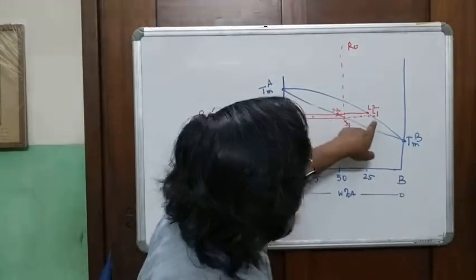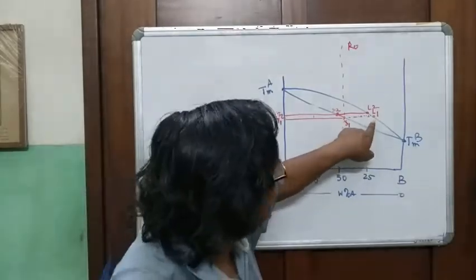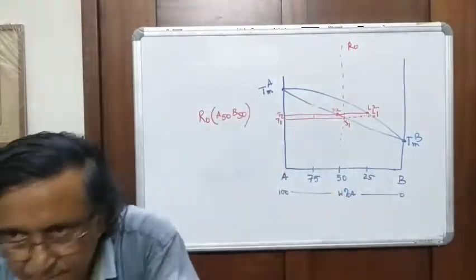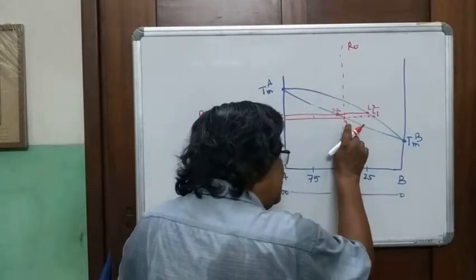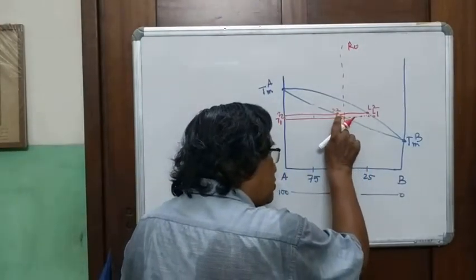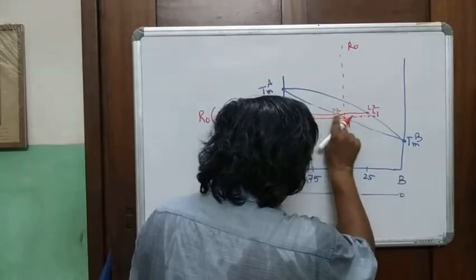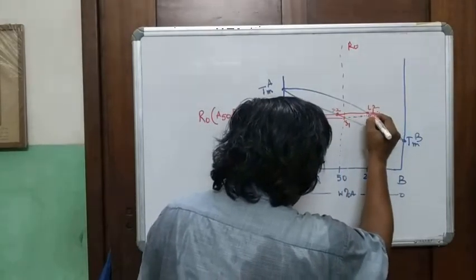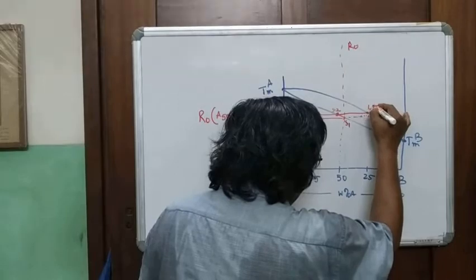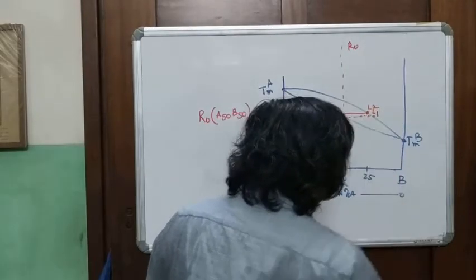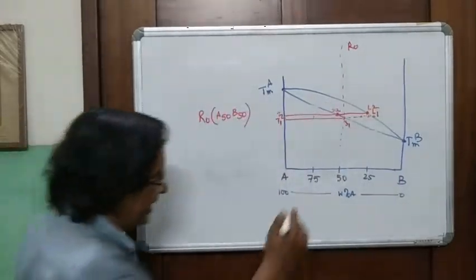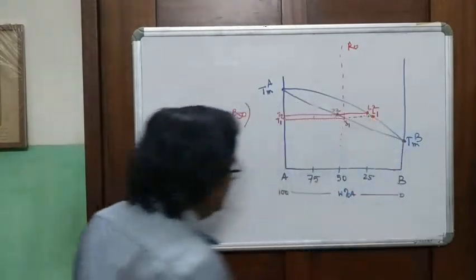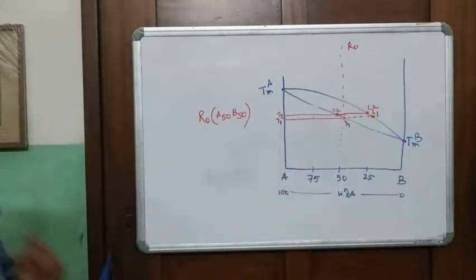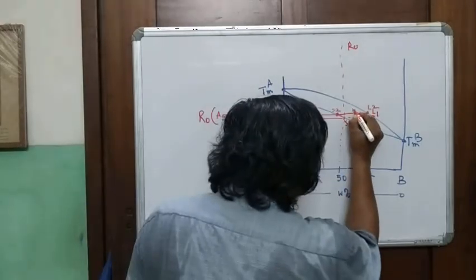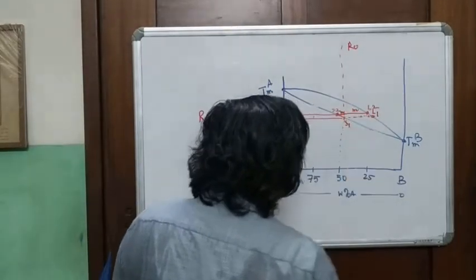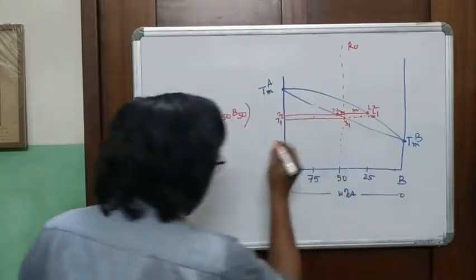S2 should be in equilibrium with a liquid L2 at another temperature. S2 cannot be in equilibrium with L1 because L1 is stable only at a different temperature. So if the S1 composition changes to S2, then at S2 you draw an isotherm and it should intersect the liquidus at L2. And this should be your new composition of the melt. The initial composition was L1. And now you see this. I write M and this is N.